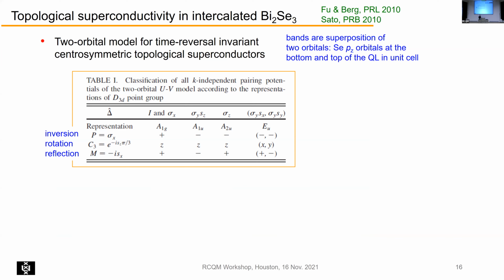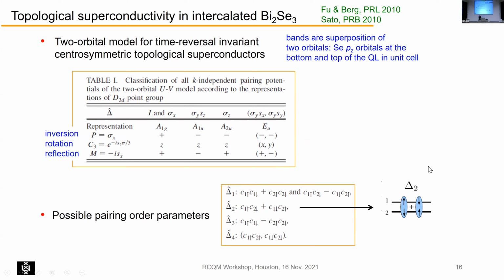And if you do the symmetry analysis, so group symmetry, where you have inversion, rotation, and reflection, so you have actually three one-dimensional representations like here, and you have one two-dimensional representation. Now, in the first work, also on the copper-intercalated Bi2Se3, Fu and Berg actually posed that this would be the state, which is relevant here. So this is the delta 2 states, which is selenium atoms of PZ orbitals in this spin up and spin down in a linear combination with spin down and spin up. So that is this. This is like the LZ equal component in the triplet state. So we have 4 different states. So they go under the name delta 1 to delta 4. This is the singlet state, and this is the Eu states, which is a 2-component order parameter.